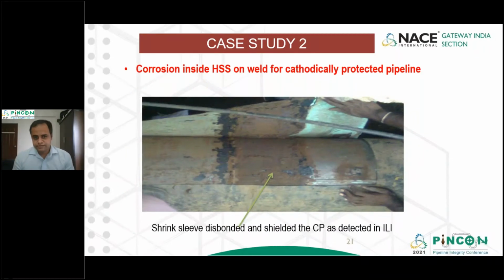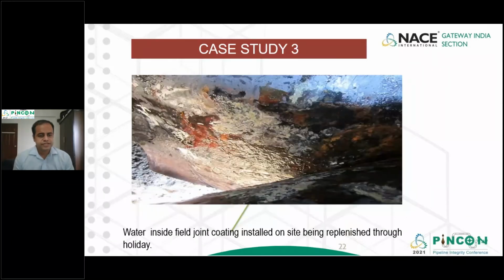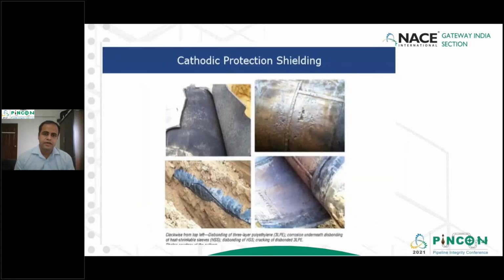Corrosion inside heat shrinkable sleeve at the welds. You can see that a cathodically protected pipeline is having a weld wherein the heat shrinkable sleeve was applied in the field. And instead of having cathodic protection, a severe amount of corrosion has happened in and around the weld area, which is observed only when we tear up the weld, and this was detected in the ILI. Case study 3 is all about water inside field joint coating installed on site being replenished through a holiday. So again, water has come inside and it has started corroding the pipe. And finally, these are some of the snapshots which you got from the field because of the cathodic protection shielding phenomena, wherein the current could not penetrate inside the holidays in the coating.